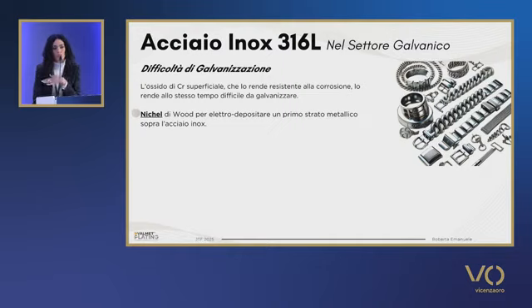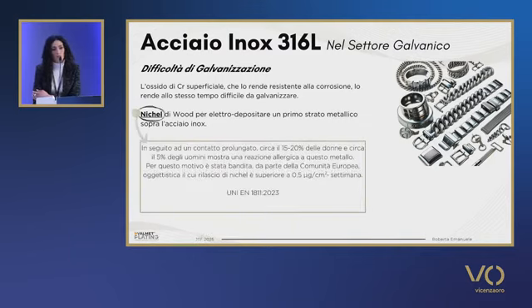Usually, to coat this type of steel, nickel wood is used. This is a material that has many additional problems. Once in touch with this material, different percentages of men and women develop allergies. This is why it was banned by the European Union in the case of the nickel release being higher than 0.5 micrograms per square centimeter per week. This is the amount which may provoke an allergic reaction.